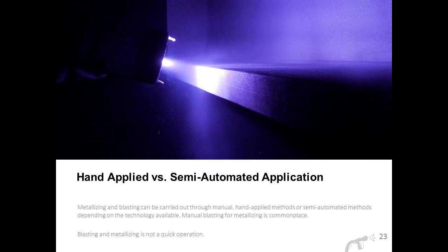Both blasting and metallizing can be either hand-applied or semi-automated depending on the type of equipment available. I would say for the most part, to get a really nice and even surface through metallizing, semi-automated is a good way to go. However, in order to get the right profile for blasting, you'll typically find that hand blasting is the dominant method for achieving the profile. It's also important to keep in mind that that's not a quick process. It's a pretty lengthy process that takes some time. So that's something to consider when choosing your corrosion protection options.